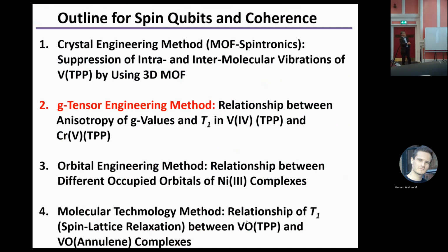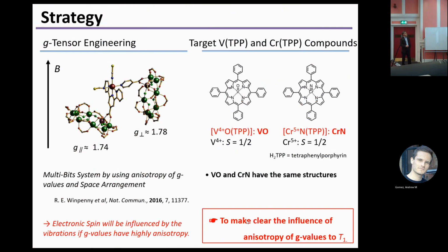The relationship between anisotropy of g values and T1 in oxovanadium TPP and chromium nitride TPP. The original g-tensor engineering means a multi-qubit system using anisotropy of g values and spatial arrangement, developed by Richard Winpenny in Manchester. But we use it because the electron spin will be influenced by the vibration if g values have high anisotropy. So I focus on oxovanadium TPP, spin 1/2, and the chromium nitride, spin 1/2. Both have spin 1/2, to make clear the influence of anisotropy of g value on T1.